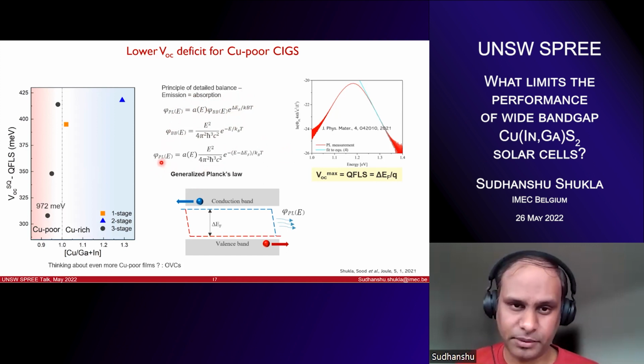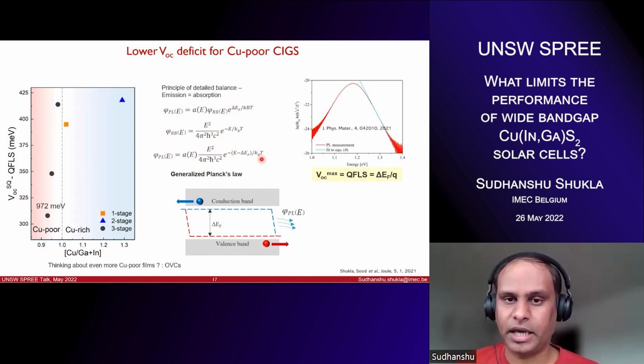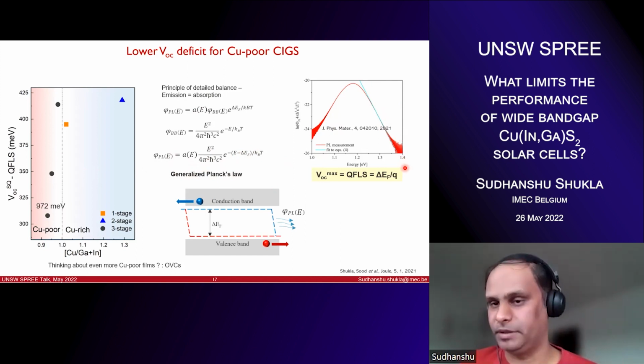If you just plug it in, you get this formula. So the flux from the PL is given by the absorptance times this constant term and this quasi-Fermi level splitting. So one can do the fitting. If you take the log on both sides, you can fit it and determine the value of delta EF, the quasi-Fermi level splitting. And this is also called the generalized Planck's law. So this is how we determined our quasi-Fermi level splitting.